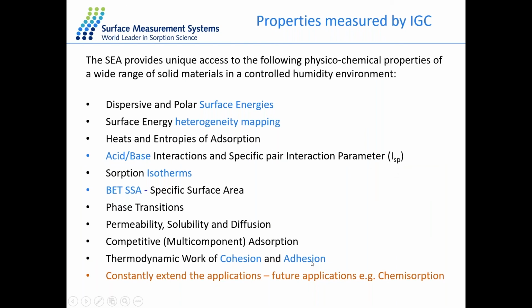So here are just some properties to be measured with IGC technique. If we just do a single organic vapor injection at different concentration, then we can get the absorption isotherm of this organic vapor, for example, the octane isotherm. So from the isotherm, if it's a type 2 or type 4 isotherm, we can then calculate the BET surface area of this material. And if we are selecting different kind of solvents for different interaction, both the nonpolar probe and the polar probes, we can then get the dispersive and the specific surface energy of the material. And because we are doing the injection at different concentrations, we can get a distribution of this surface energy on the surface, a heterogeneity mapping on the surface of this material.